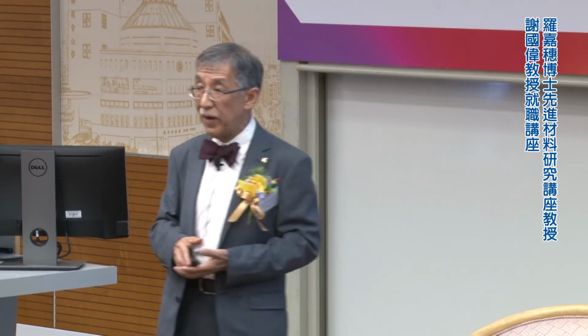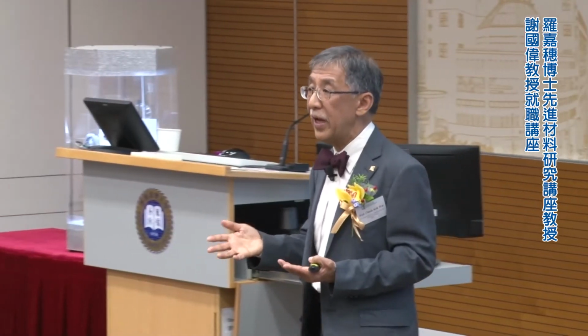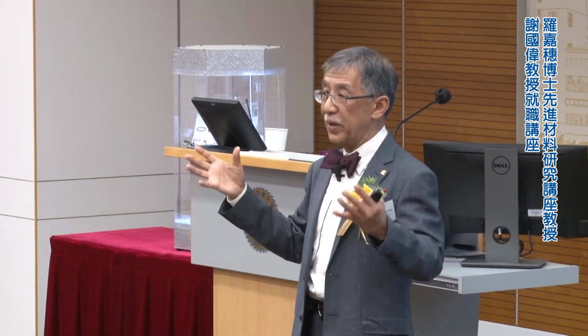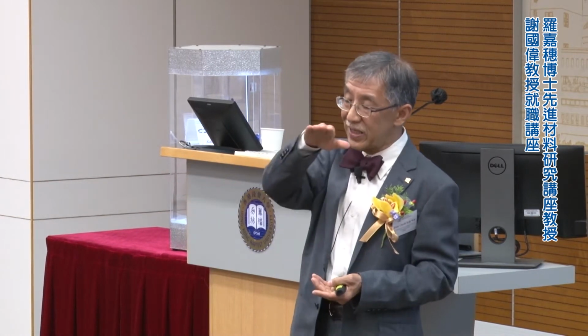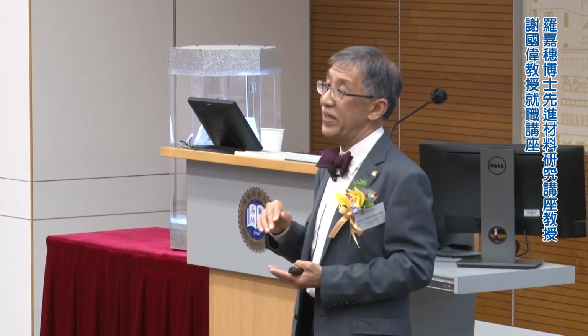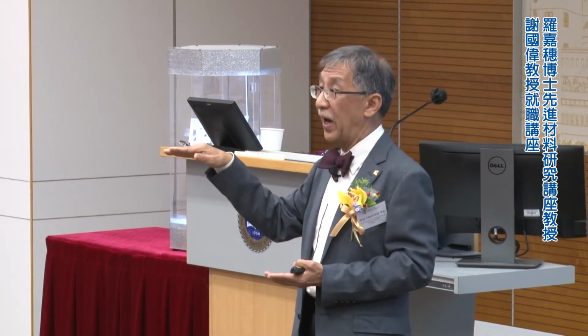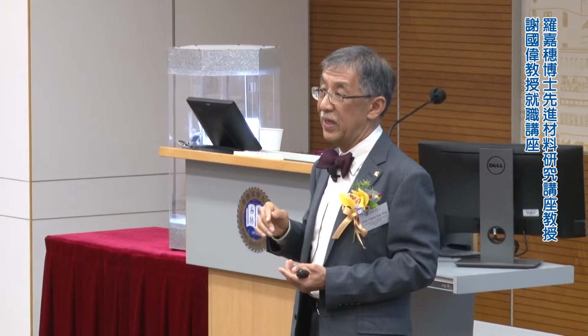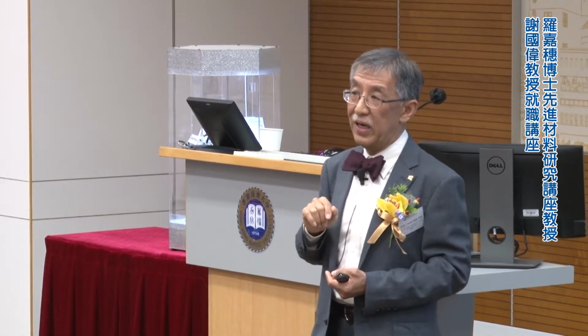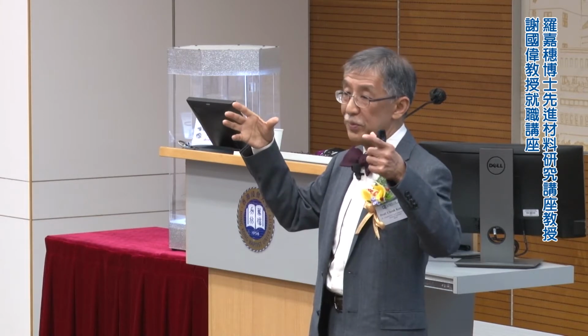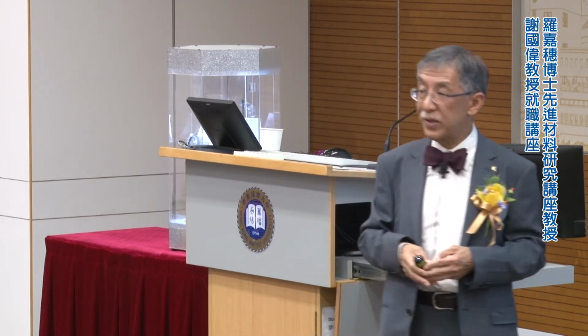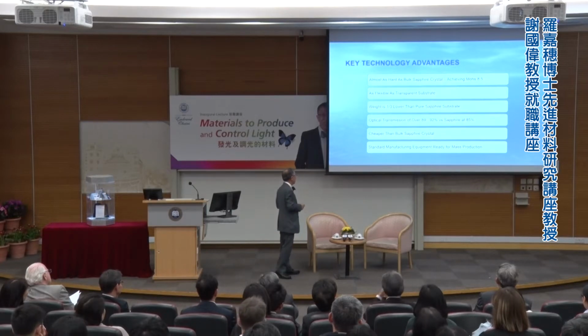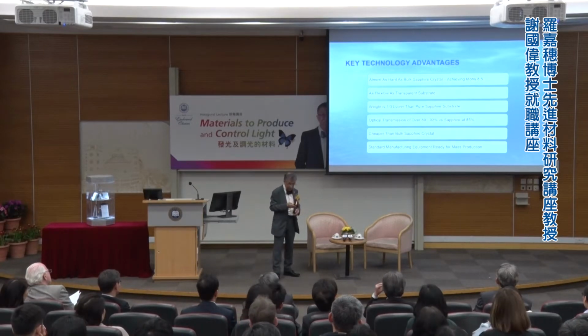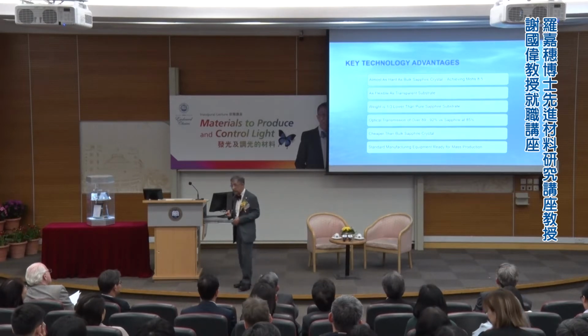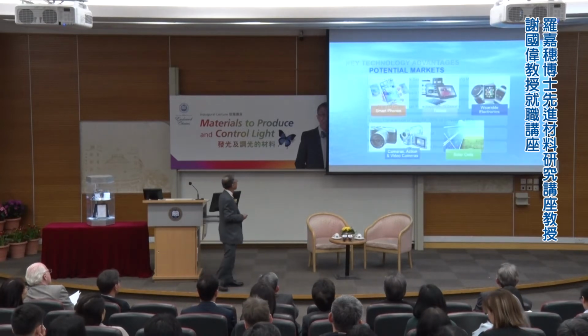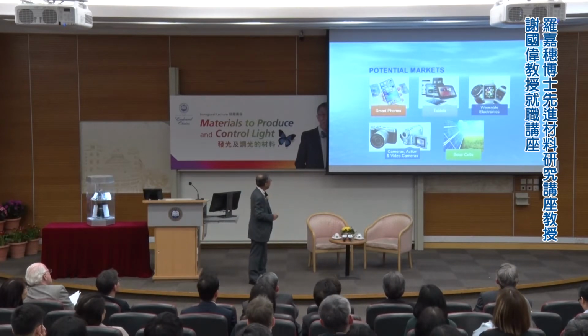And of course, it's cheaper than sapphire crystal, because sapphire crystal normally will take you at least 2 weeks to grow. And because sapphire is second hardest, you can only slice it using diamond paste. And that also takes a long time. And then polish it. And when you get to very thin, they can break, because being hard also means it's fragile. So it's costly. And as I mentioned, we're using standard manufacturing equipment, so that can be adapted for mass production easily. And potential markets have all this.